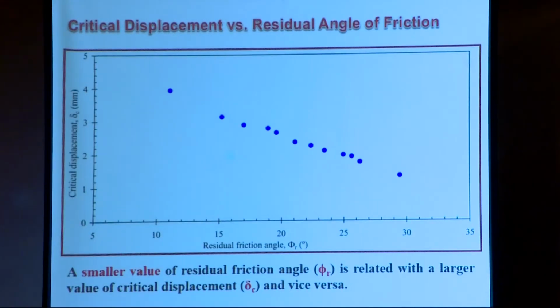And what you obtain finally is this. The mechanism should be: below the critical displacement, we have a static state of friction, and after the critical displacement, you have the influence of dynamic friction. So this is how we define critical displacement. And when you have a graph of residual friction phi r versus critical displacement, you get a straight line like this. That means stronger soils have less critical displacement. Weak soils have greater critical displacement.